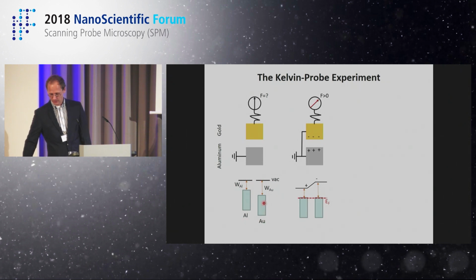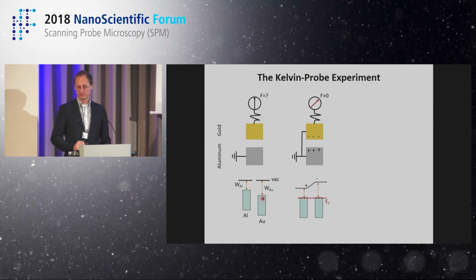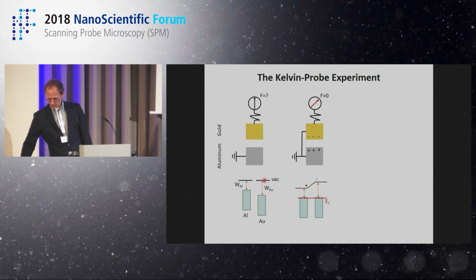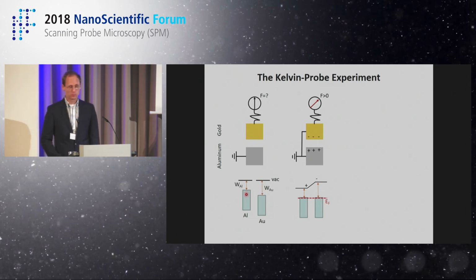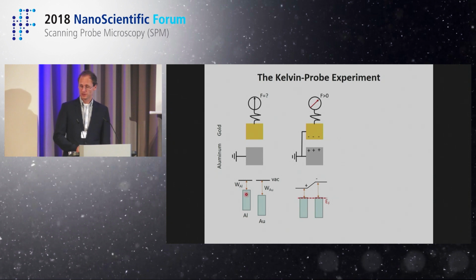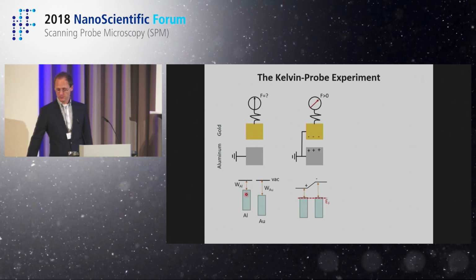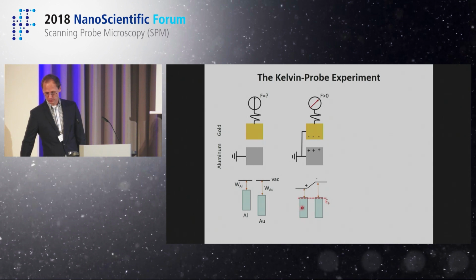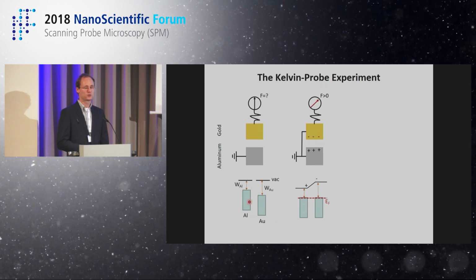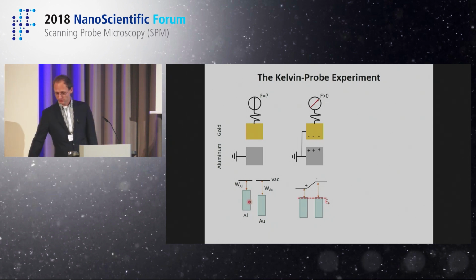It means that if you have a noble metal, you need a lot of energy in order to remove an electron from the metal. That's the so-called work function, which is large for gold. If you have a not so noble metal like aluminum, we all know this, you basically need very little energy to remove an electron from it. Now, if you put the two of them into contact, as shown here, the electrons feel that in aluminum they are not so stable, they could be more stabilized in gold, so they flow across your cable and move into the gold.